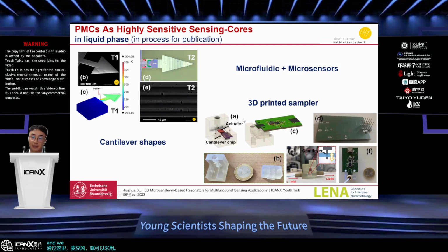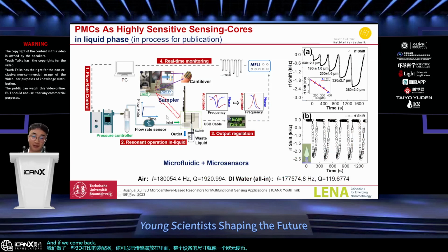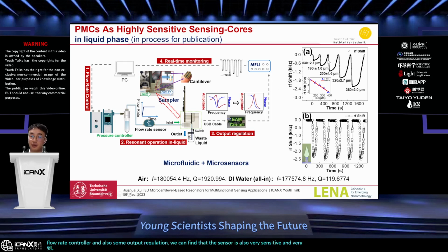And we made some 3D printed assembly, in which you can put the sensor inside, and the whole device size is like a 1 euro coin. And if we combine this device with the flow rate controller and also some output regulation, we can find that the sensor is also very sensitive to the microfluidic, to the microflow change.